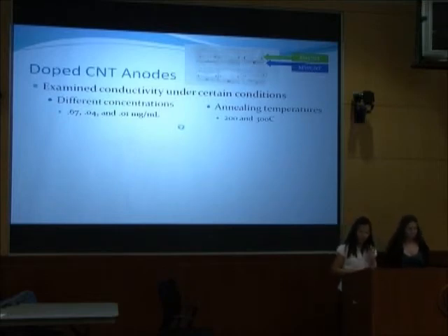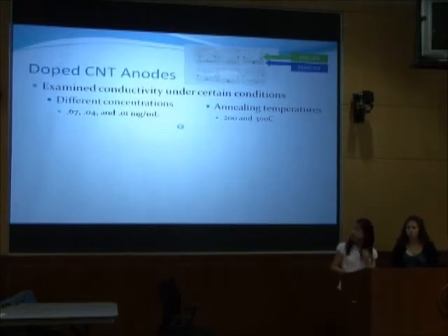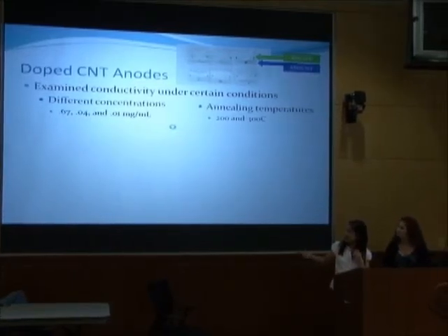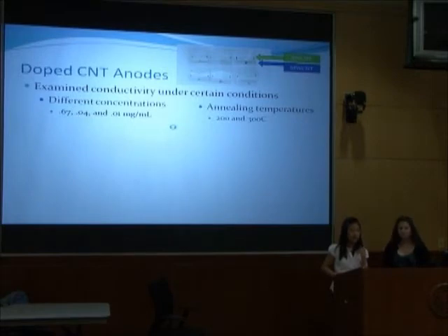So basically in our experiment, we started off by finding the best doping conditions. We tested different concentrations. You can see the concentrations up there. And we also tested different pre-annealing temperatures for the nanotubes before they were doped.